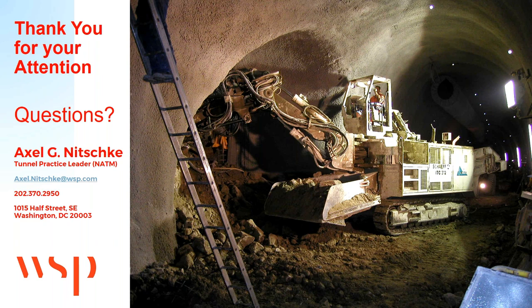That was absolutely fascinating. The first question is: what would be the thickness of the sacrificial layer when applying Shotcrete on frozen ground, and how do you determine it? The problem with frozen ground is basically that the water in the mix freezes and cannot react with the cement anymore, so you don't get the final strength you're looking for. I would guess that you need a few inches as a sacrificial layer, but if you really want a hard number, feel free to shoot me an email and I can do some more research.